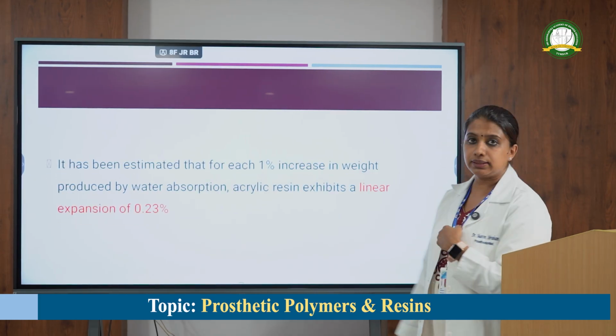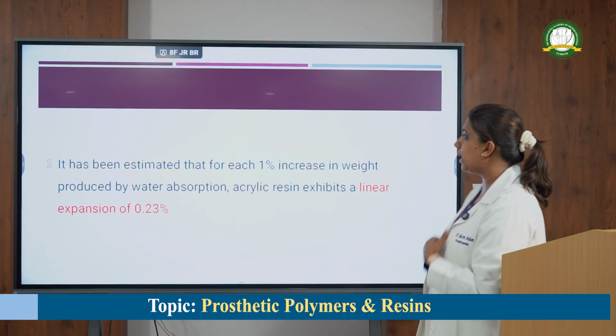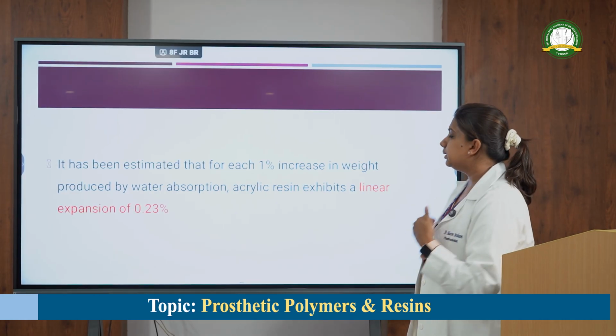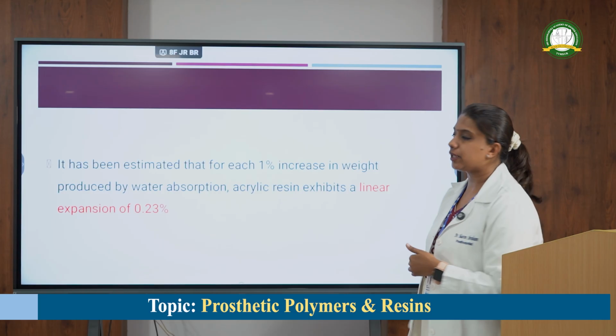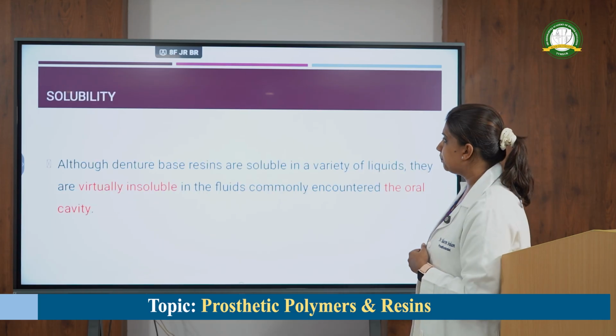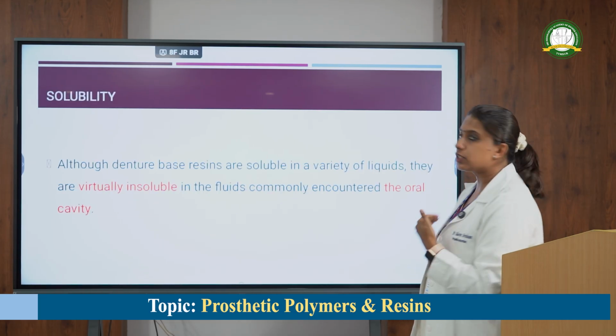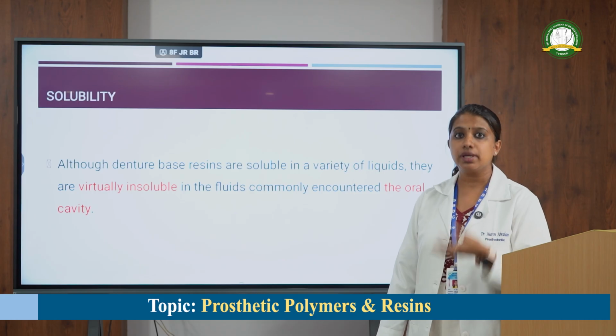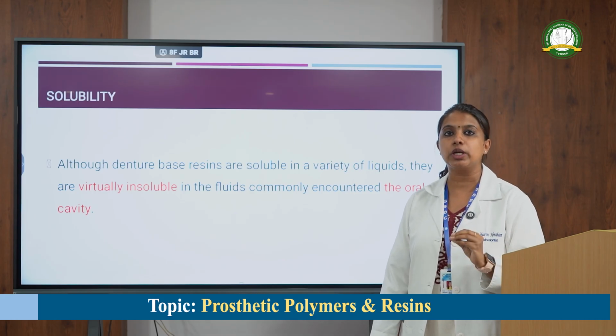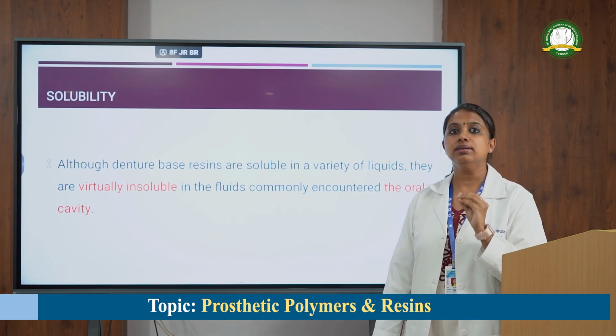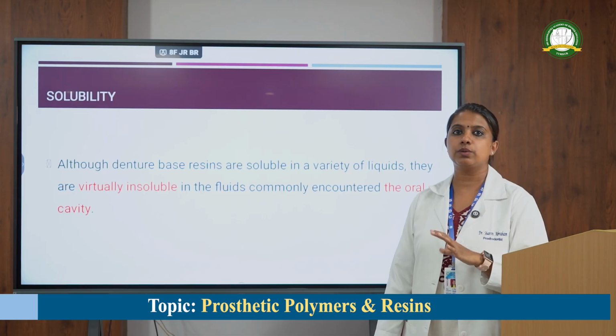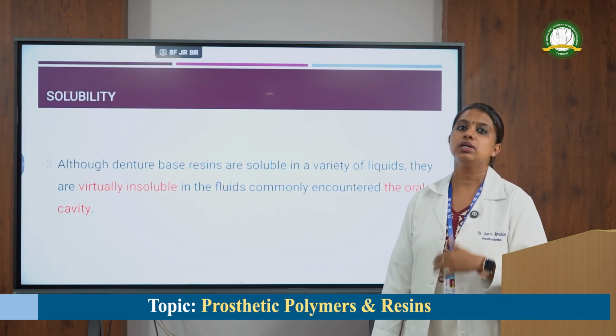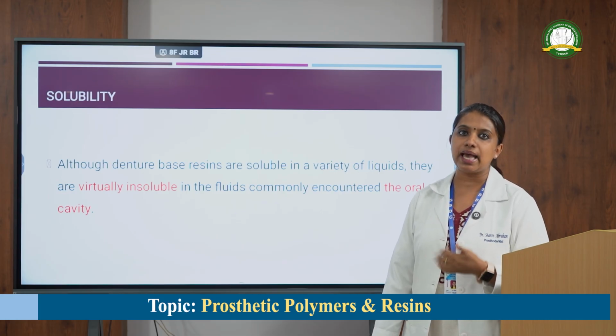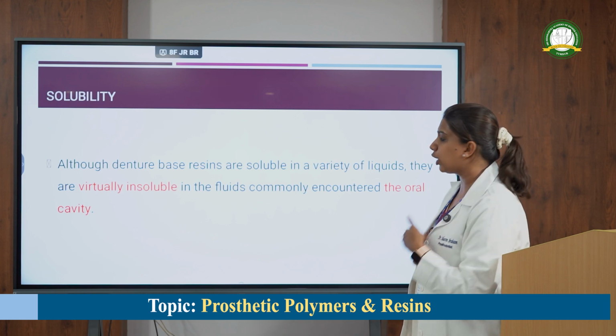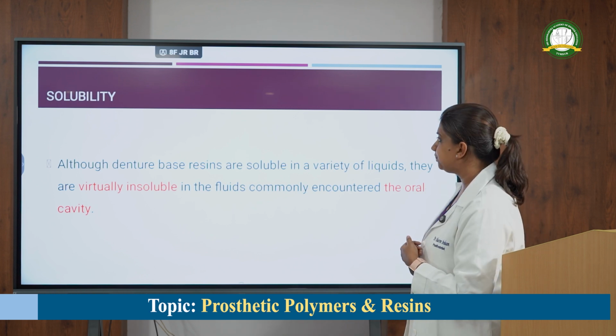It has been estimated that for each 1% increase in weight produced by water absorption, the acrylic resin showed a linear expansion of 0.23%. Although denture base resins are soluble in a variety of aqueous media, it was found that they are completely insoluble in the oral cavity or in the saliva. That's why it was found to be the best material for the fabrication of complete dentures, as it is insoluble in saliva or any kind of oral fluids.